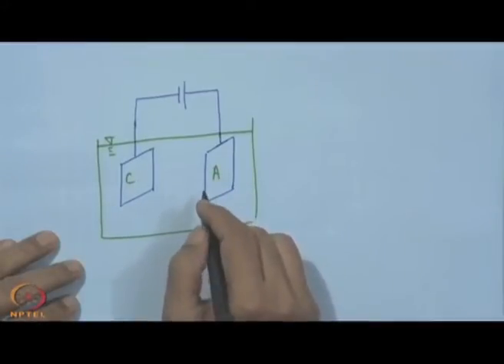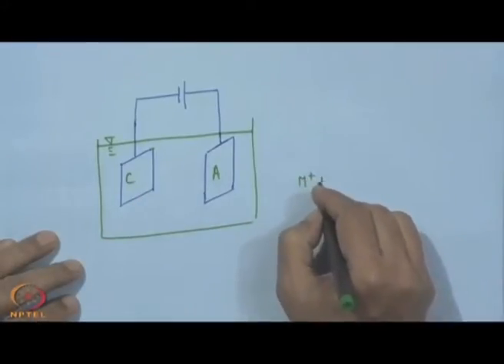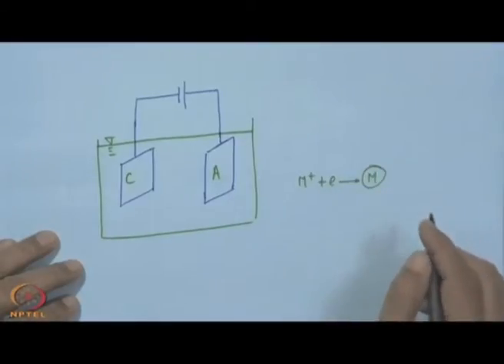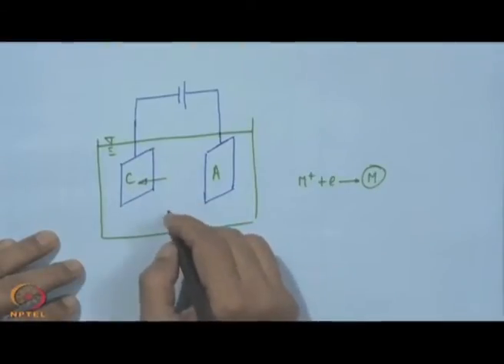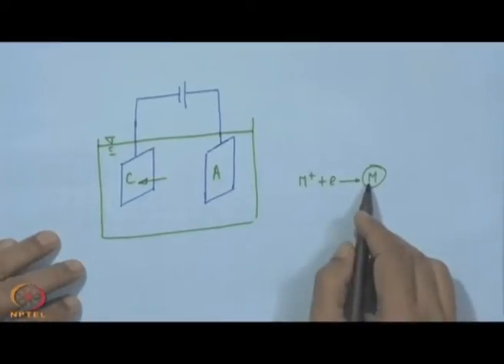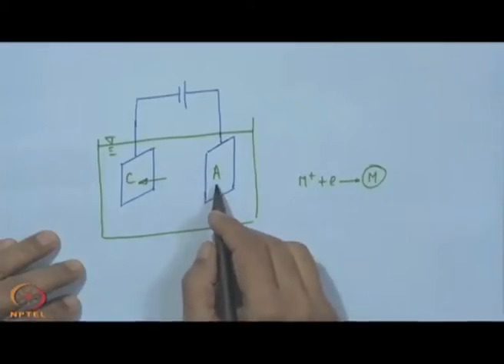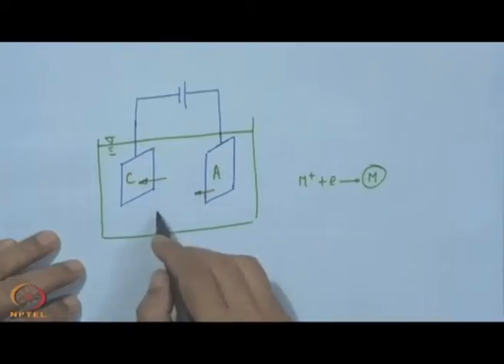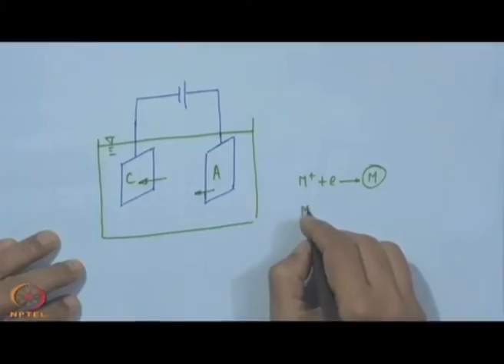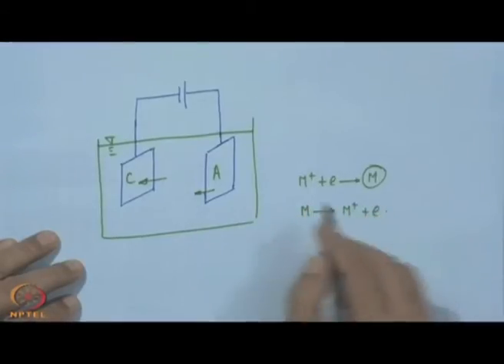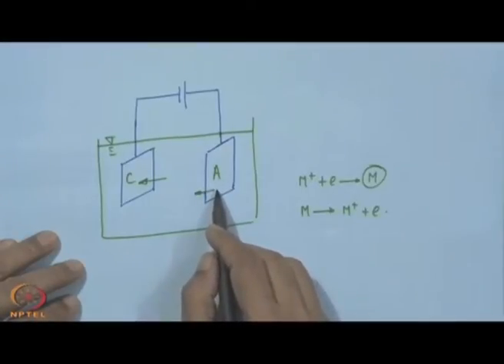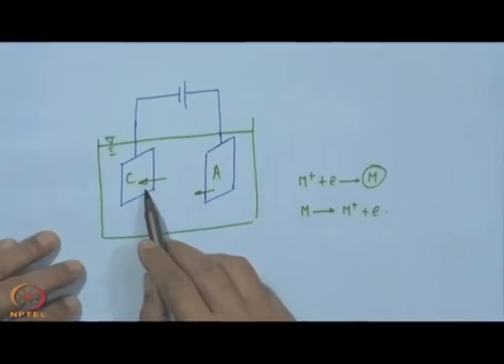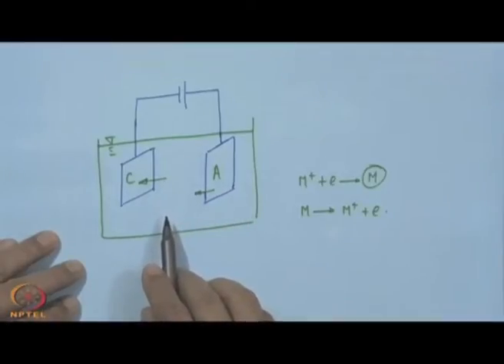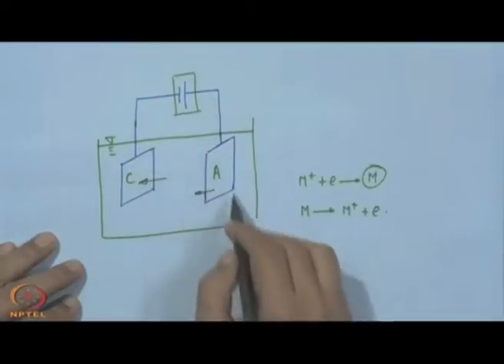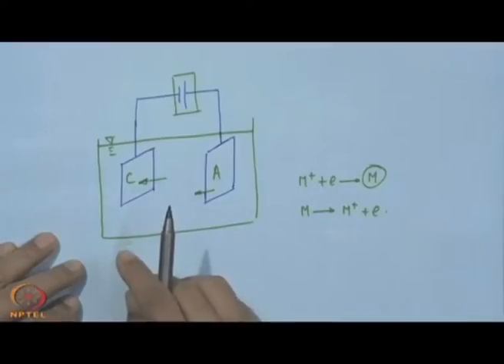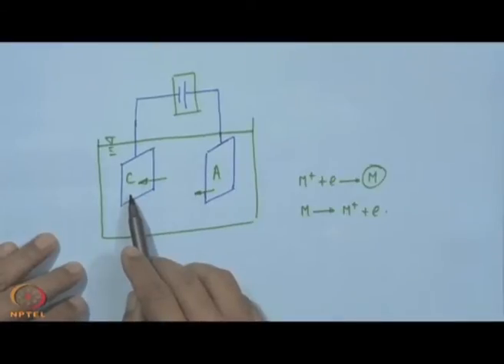So, metal will be deposited on this cathode by the following reaction: metal ion plus electron gives the neutral metal, and that will go on this side. During this process the solution will become deficient in that metal, but this will be continuously replenished by the continuous erosion of the anode, which is of the same metal as the metal in its salt solution. So, here it will be metal ion plus electron. So, there will be an anodic reaction, that means electrochemical dissolution, and here it will be electrochemical deposition. This way the process will keep on going, and the power source, current density, and concentration of the electrolyte are the process variables which control the growth rate or the deposition rate of the material.